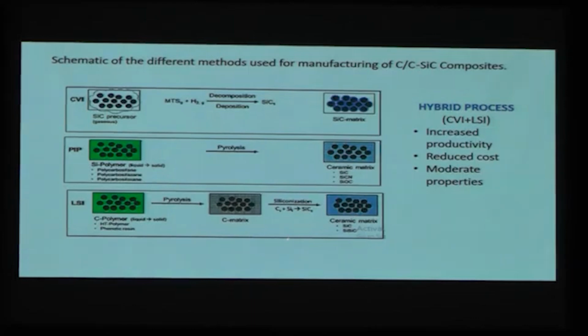The third one is the liquid silicon infiltration process, where my starting raw material is, for example, carbon-carbon composite, which is porous in nature. That one will be taken to my LSI treatment, where silicon is kept along with that by calculating the stoichiometric ratio, so that the available carbon will react with the silicon and form silicon carbide. So thereby I reduce the time. So I use all the three. In my hybrid process, I use the first one for interface coating, and the second one for getting the carbon-carbon porous matrix. The third one is for the final process, the final composite.